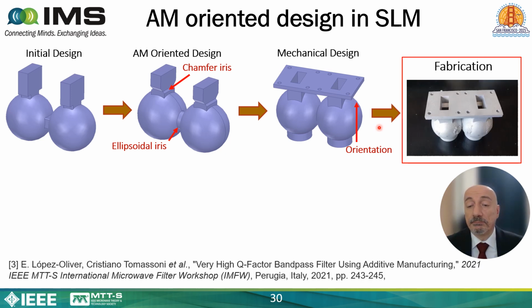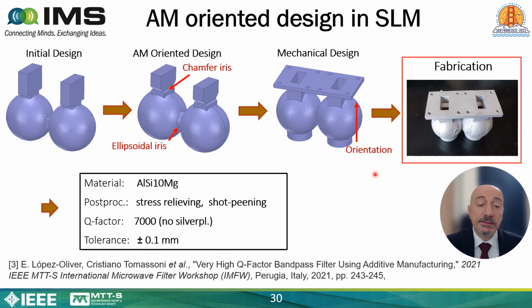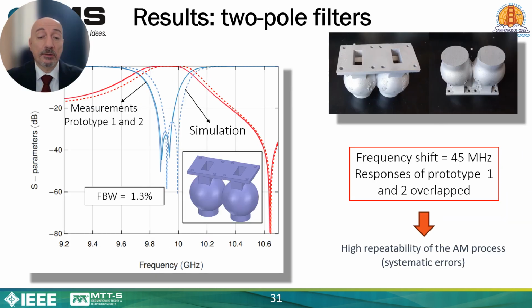This is the final result, and as you can see, we obtained very good results in terms of Q factor, because the Q factor of this filter was 7,000, and to my knowledge this is the highest Q factor ever obtained by using an additive manufacturing technology. There is no time to explain better how it works, but you can find more details in this paper. This slide shows the comparison between the measured results and the simulated results.